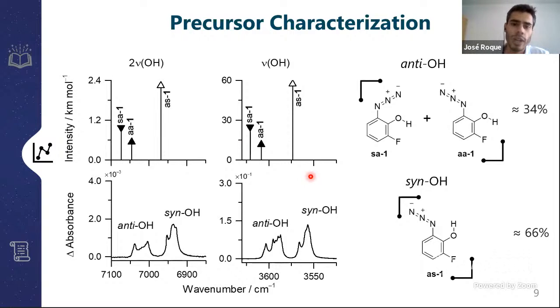the OH stretching vibrations, both the fundamental and the first overtone, the experimental spectra and the theoretical spectra based on some DFT calculations. And what we observed was that there were two completely distinguished bands, one for syn-OH and another for anti-OH. This latter one also includes the overlapping contributions of two conformers, and we estimate that more or less one third of the total population of this azide should have anti-OH conformations.